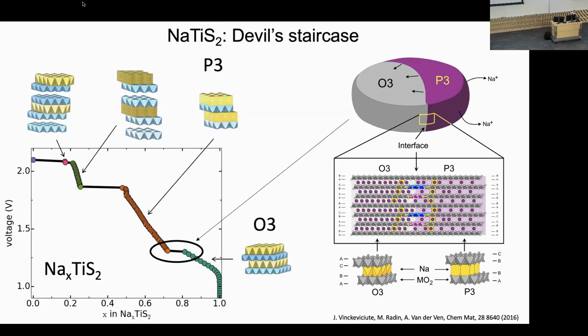And so at the particle level, one way you can do that, crystallographically, is to create these partial dislocations, in a fairly complicated network, positive, negative, and some planes that are unaffected. You have all these little dislocations along this interface separating P3 from O3, and these little dislocations have to migrate through the crystal as you're pulling sodium out to form the P3. So instead of a mechanical deformation causing dislocations to move through the crystal, it's actually a chemical removal of atoms.